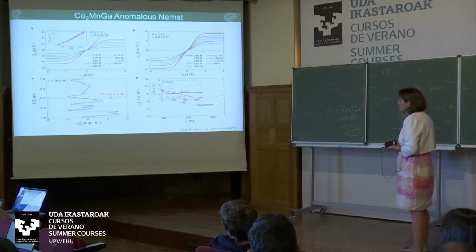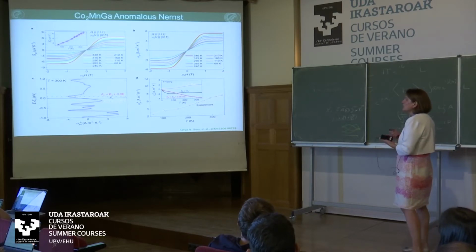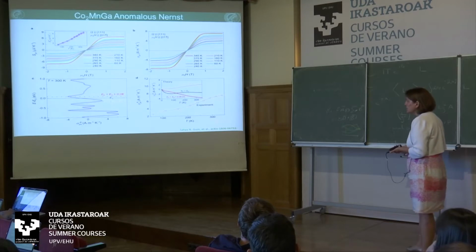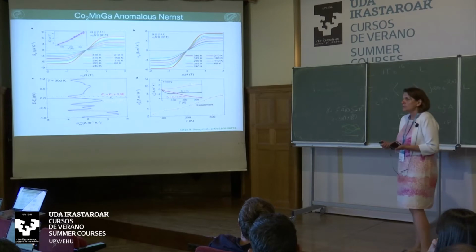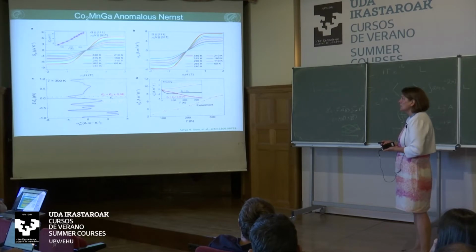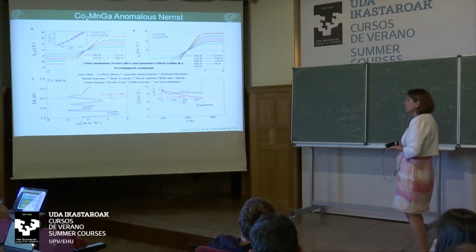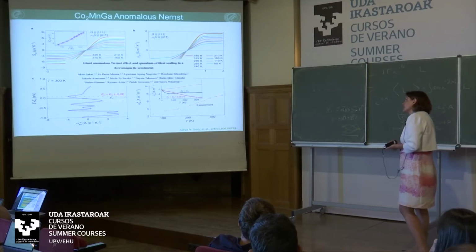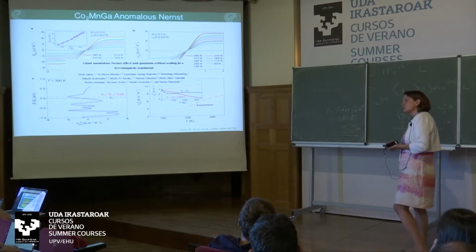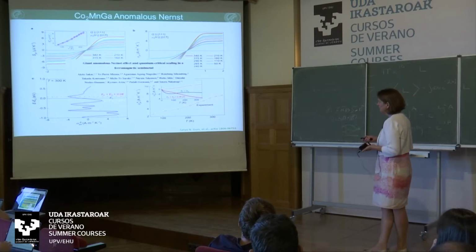And you see, even as a function of temperature, it's increasing. It's 6. I will show you in comparison to other magnetic materials that this is really giant. But you see, since Tc is somewhere here at 800, it might go up to 10. So it's really much larger, more than an order of magnitude what we know from other magnetic materials. And at the time when we were publishing this on cond-mat, slightly after us, another paper was published on cond-mat, also working on giant Anomalous Nernst effect, which was now published in Nature Physics, face-to-face with another paper of ours, but this is still struggling.